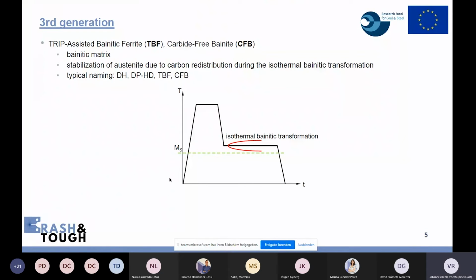Here you can see a typical annealing cycle for TRIP-assisted bainitic grades, the TBF grades, and for carbide-free bainitic grades respectively. And one very important step during the annealing process is the overaging step. That means the isothermal bainitic transformation step, where stabilization of austenite due to carbon redistribution is performed. Typical naming for these TBF grades, for these CFB grades, are dual phase high ductility grades, DP-HD grades, and as I said, TBF for CFB grades.